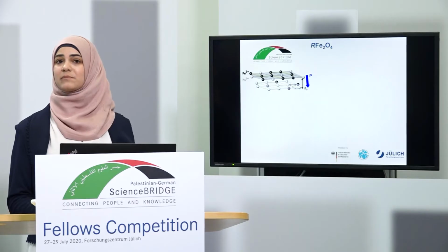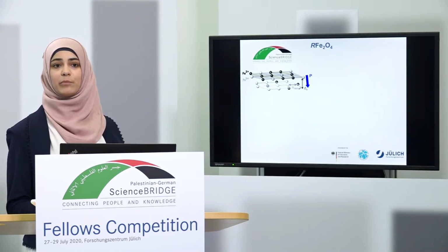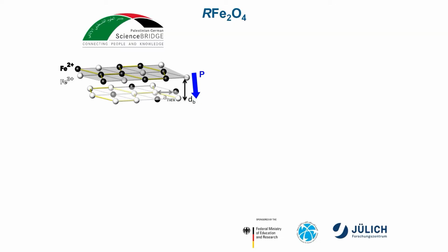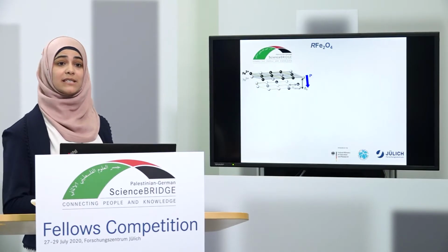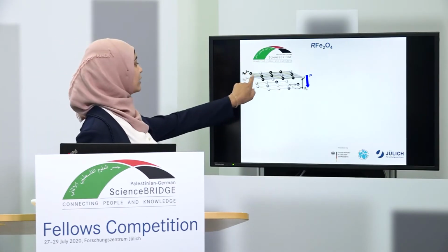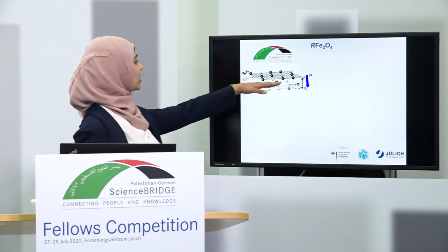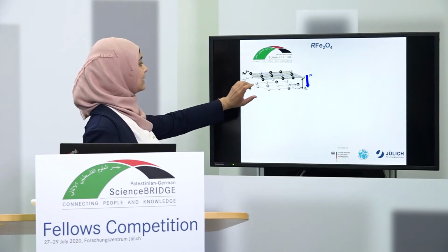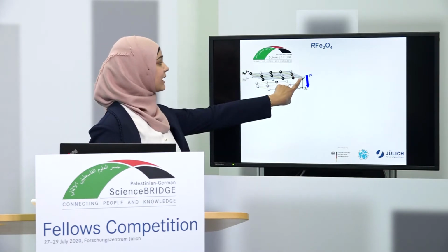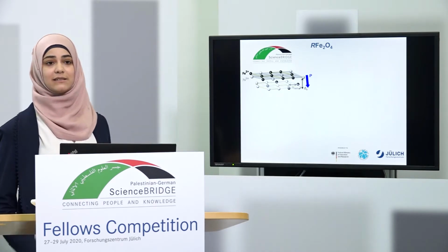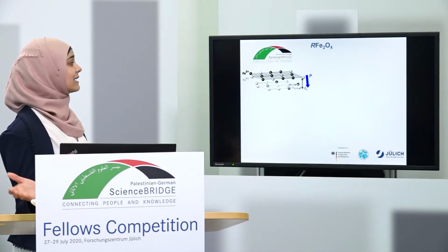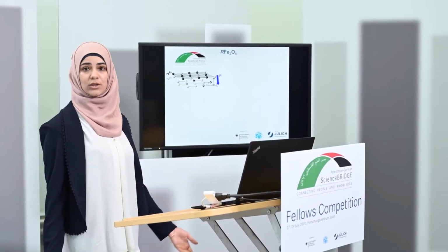Why am I focusing on these multiferroic materials that are driven by charge order? Because there was a proposal in 2005 by Ikeda that this lutetium ferrite compound, which has this basic structure, is ferroelectric. Basically, because this compound has different valences of the iron, +2 and +3. The arrangement of these different charges in the bilayer leads to a charge difference separated by the distance you see here, the thickness of the bilayer, and this leads to an electric dipole and so polarization.